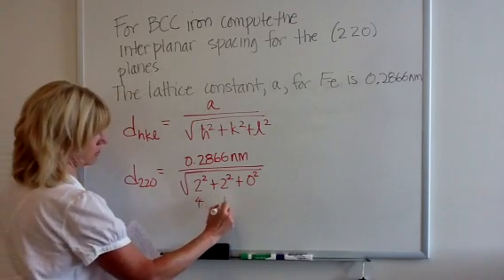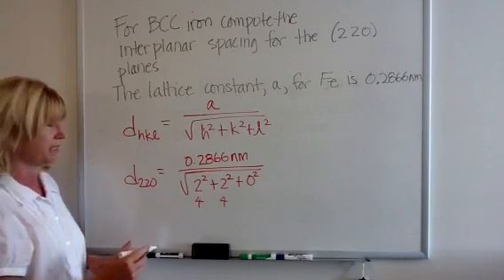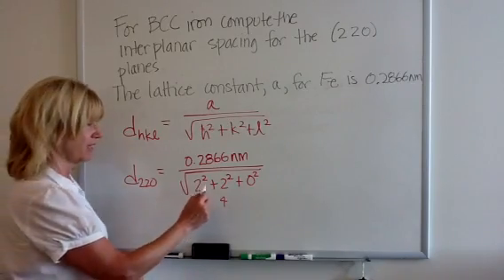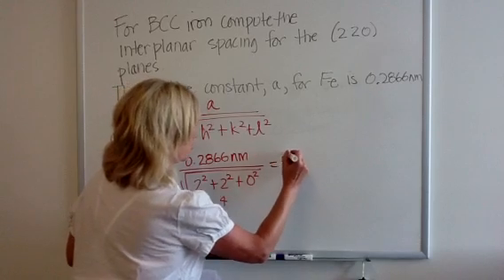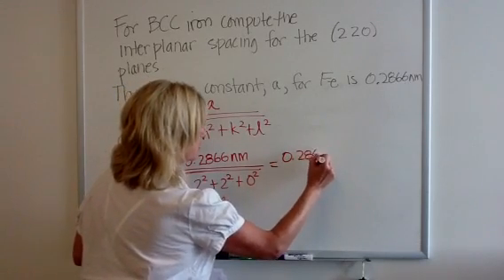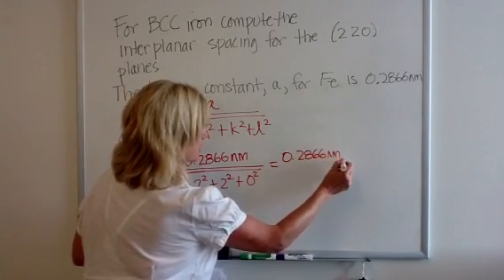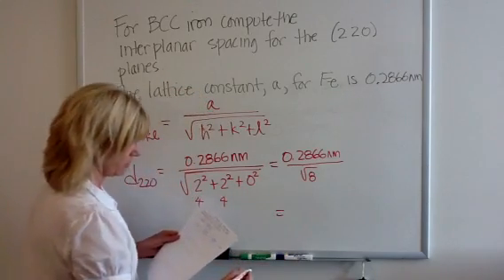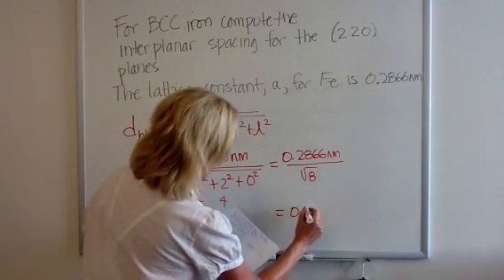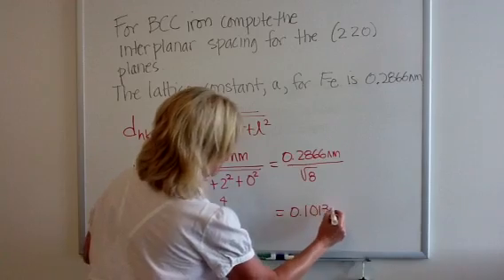So this is 4 plus 4. I always write this down because I have found that a lot of times we do these in our head and we don't add them up right. So this is 0.2866 nanometers over radical 8 and I calculate that to be equal to 0.1013 nanometers.